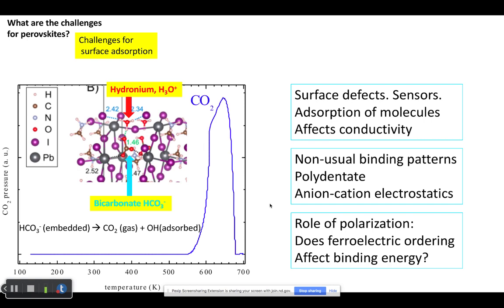And also there is an unresolved question. The perovskites, I'm skipping the introduction, are inorganic scaffolds with either organic or inorganic cations that can either translate or rotate inside. And this is a very polarizable material with a high dielectric constant. In bad perovskites it's 100, in good perovskites it's above 1000. So they're very polarizable, and depending on the internal polarization, the binding energy can also be affected.